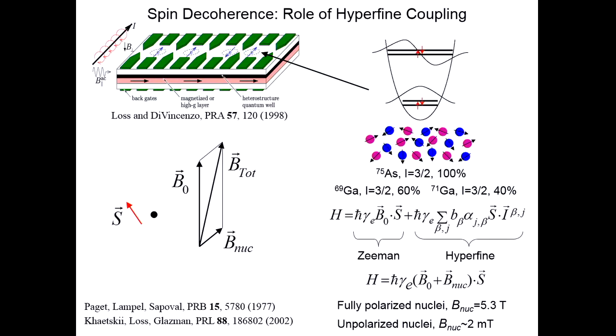And the surprising thing for gallium arsenide is if you were to fully polarize those lattice nuclei, this is a huge effect. It's the equivalent of a 5 Tesla magnetic field. It's massive. And even in a situation where the nuclei aren't polarized, you still have a couple of millitesla random fluctuating, RMS scale field. And if you convert that into time, that implies about a 10 nanosecond decoherence time. Okay, so that's the groundwork for gallium arsenide.